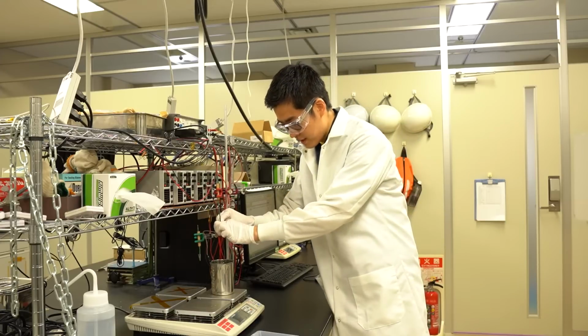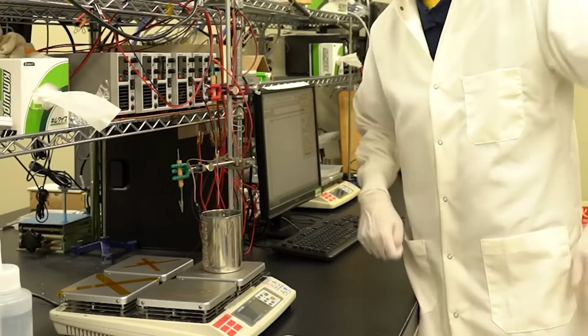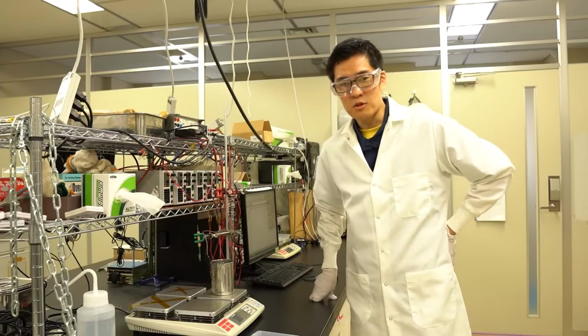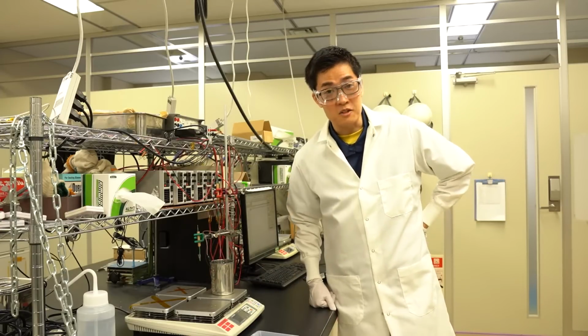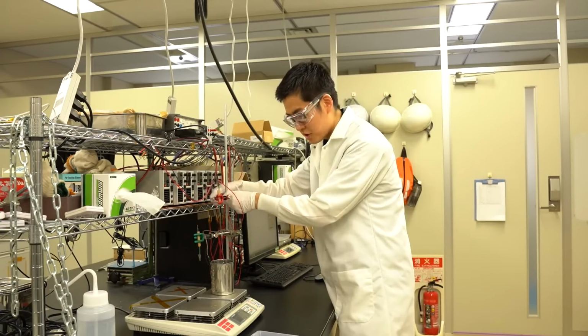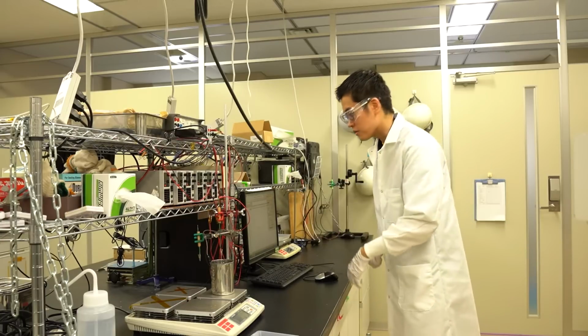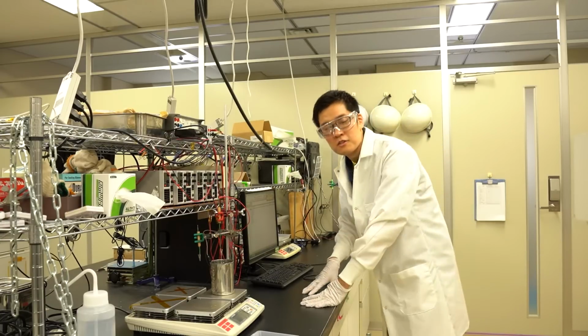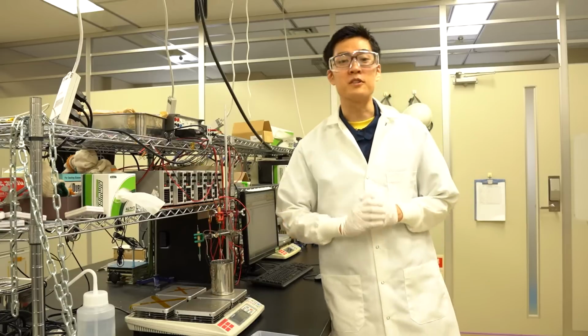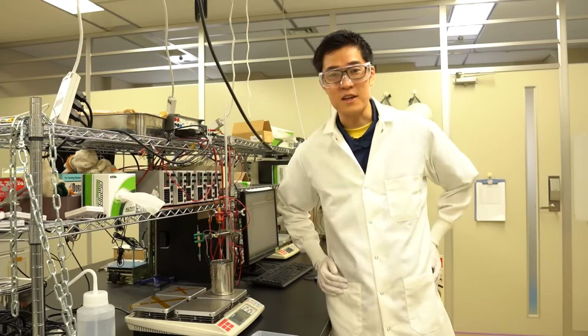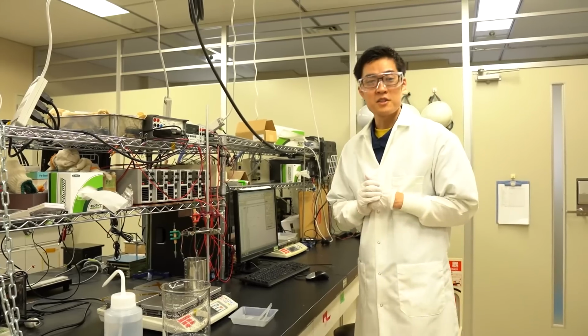Here is the aluminum foil. I'll put it in position. What's in this tin? It's ammonium adipate. It's generally known as organic acid. I'm going to dip the anode foil into the acid. When you apply voltage, the forming process begins. After turning on the power supply, we'll wait for approximately 30 minutes. This process is time-consuming. Now the forming is done.